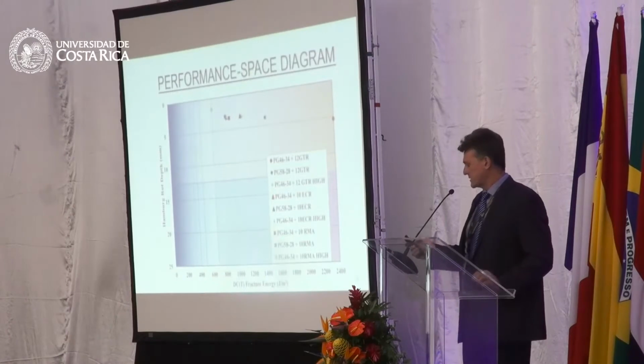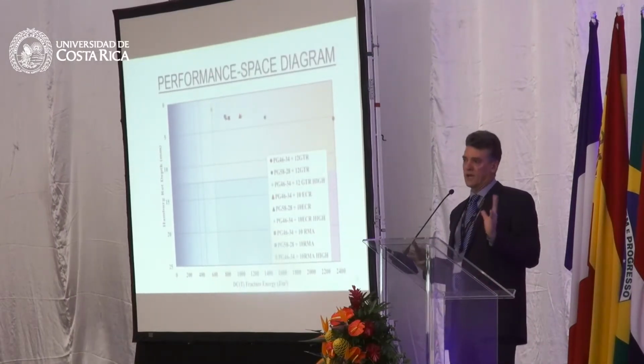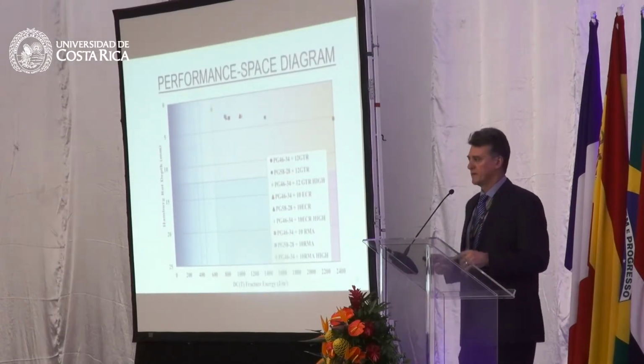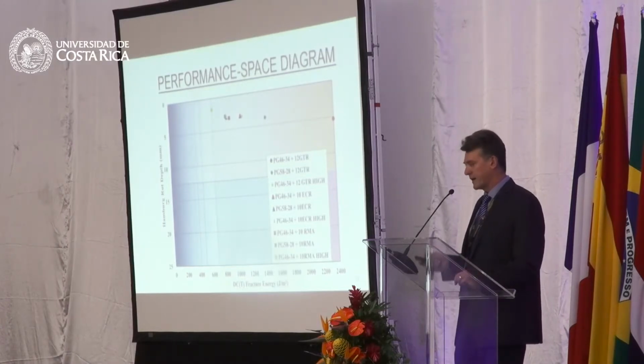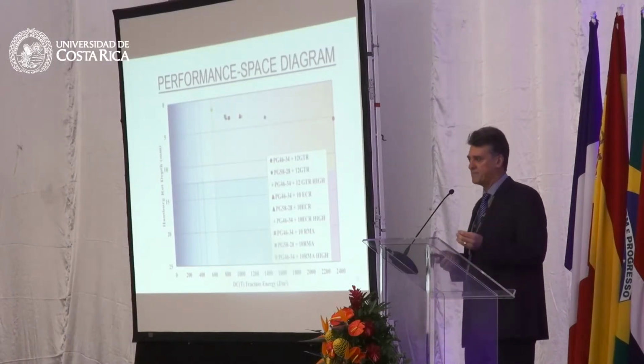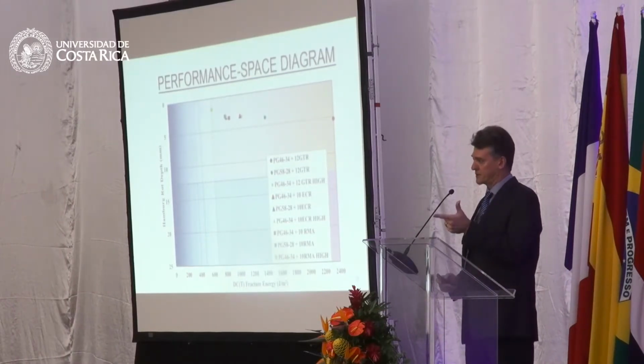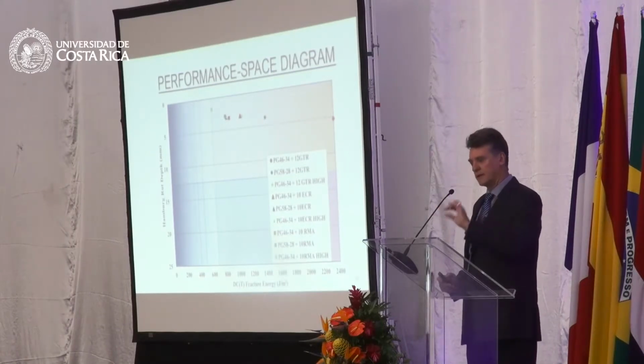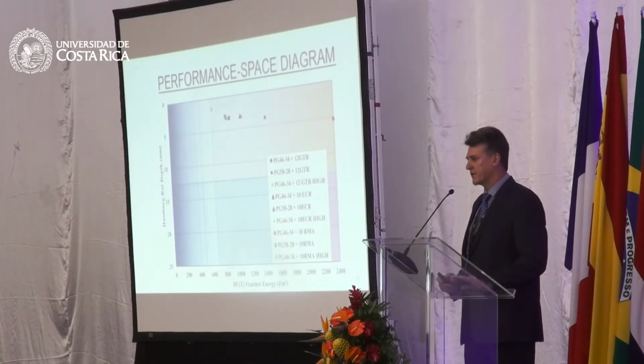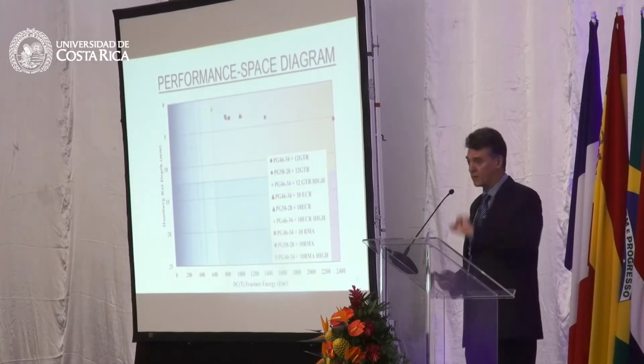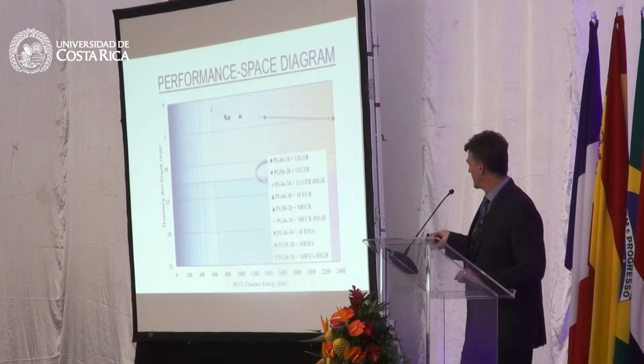But where it gets really interesting is when you plot these Hamburg and DCT pairs together on a performance space diagram. What we've seen in the past is that for a similar aggregate structure, if all you do is change the characteristic of the binder or the mastic, the points fall roughly on a line. And that's what we saw here.